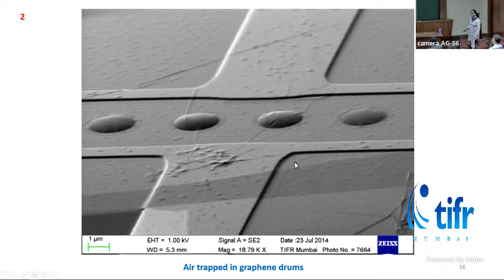So this is the test to make sure that the graphene sheet which we have laid on the sample is intact. There are no pinholes in the graphene, and the graphene layer is a continuous one. So this sample was made in Professor Mandar Deshmukh's lab.